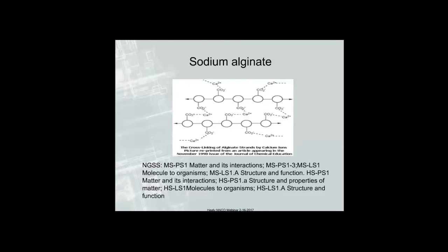But I want to talk a little bit about the sodium alginate because I think it's very important at this point that the students understand that these are cross-linked polymer spheres and that these spheres are not solid, that there are openings in them just as there are openings in cells. So think of sodium alginate as spaghetti strands or filaments. The sodium alginate strands have a carboxyl group, this CO2 minus. So it's a carbon and 2 oxygens, and it's got a single negative charge.